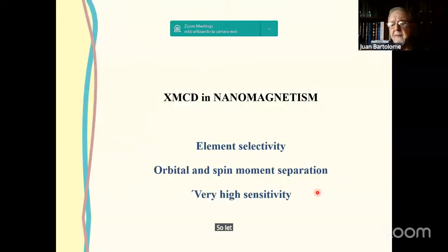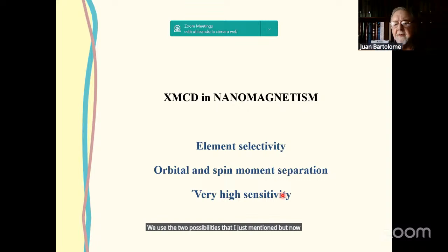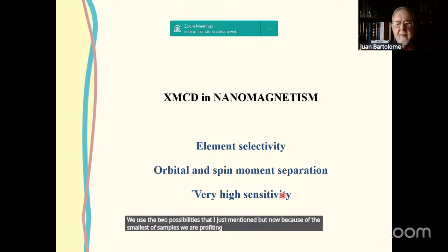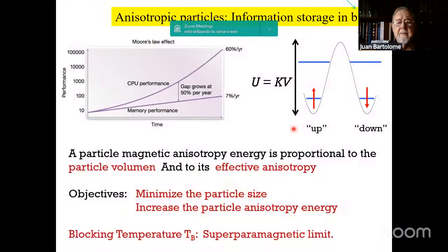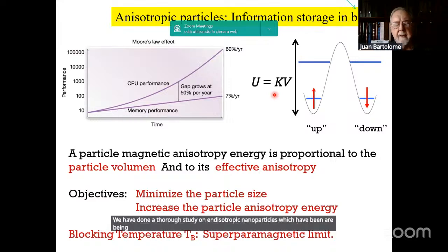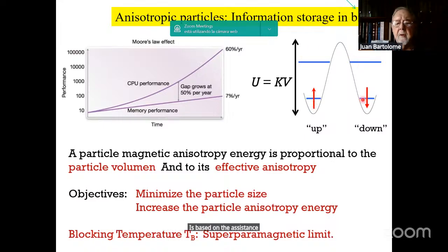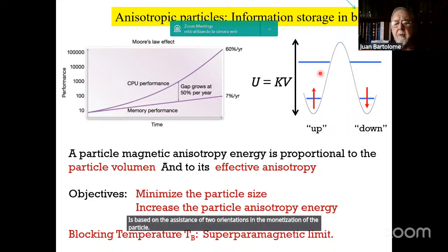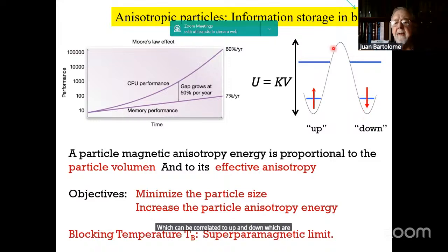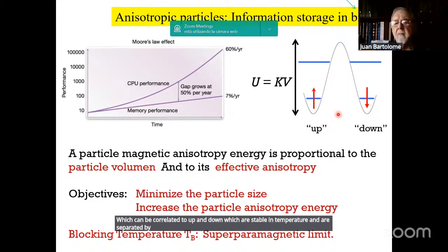So let's change of type of systems, and we go now into nanomagnetism. We use the two possibilities that I just mentioned, but now, because of the smallness of samples, we are profiting of the very high sensitivity of the technique. We have done a thorough study on anisotropic nanoparticles, which are being used as memory devices for bits. Now, its use is based on the existence of two orientations in the magnetization of the particle, which can be correlated to up and down, which are stable in temperature and are separated by a barrier which is proportional to its volume and to the so-called anisotropy constant.